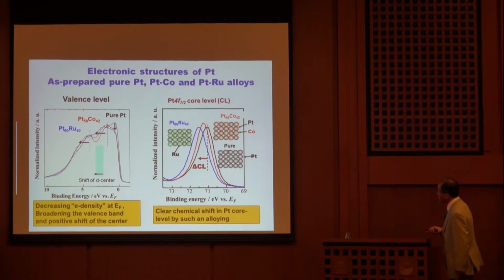So we checked the core level shift by alloying, and we clearly observed the change of the energy level from pure platinum to the alloy skin, the alloy surface. There is a core level shift. So it is a clear chemical shift.